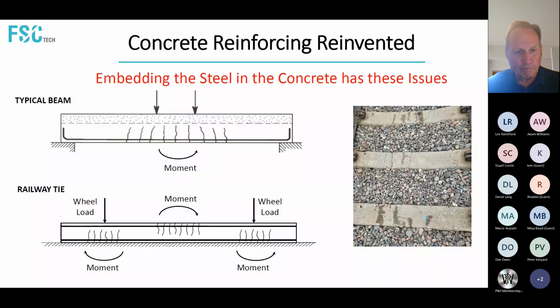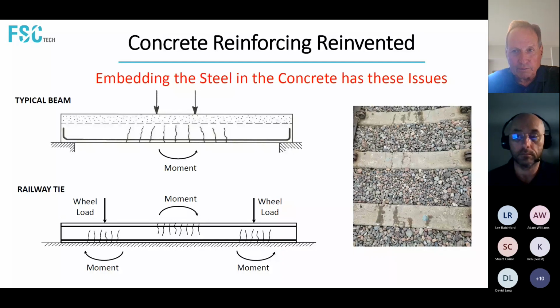And those produce a positive moment at the bottom surface of the tie where it's in contact with the ground, and produces a negative moment in the middle, which is significant because, as you can see in the picture on the right, there's a bending action there, and it's going to want to crack right around the center section of the tie. And you can see there that these are some ties that they've tried to patch on the cracks just to keep the elements from getting down into the steel reinforcement at the top.